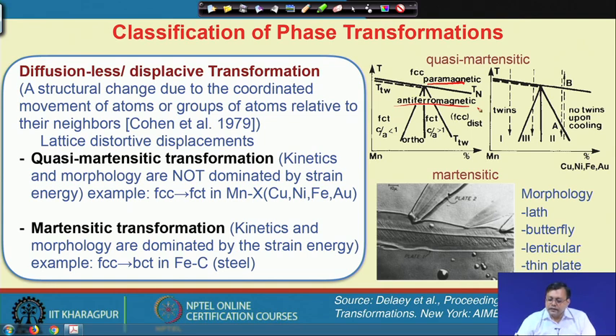Here is a paramagnetic phase which shows some sort of antiferromagnetic type of behavior. In that particular case, this is the temperature versus composition axis, and you can see the substructure that is involved in this product phase. Here the product phase is the face centered tetragonal, and the parent phase is the face centered cubic. If we think about how an FCC phase transforms into face centered tetragonal, then we simply take an FCC lattice and stretch it in one direction, maybe the z axis, or along the c axis. Then you will see that it is very easy to show how an FCT structure can evolve from an FCC lattice.